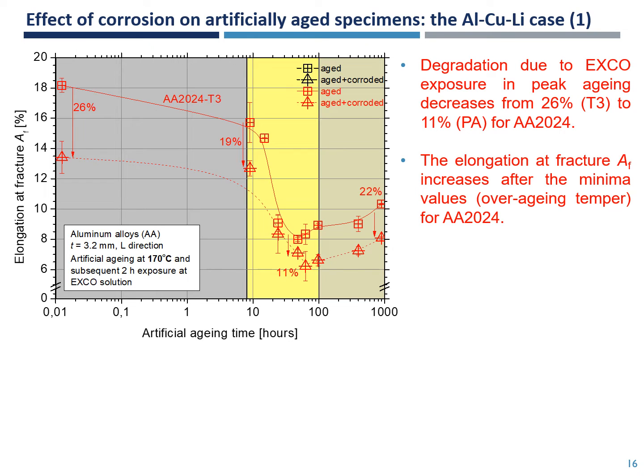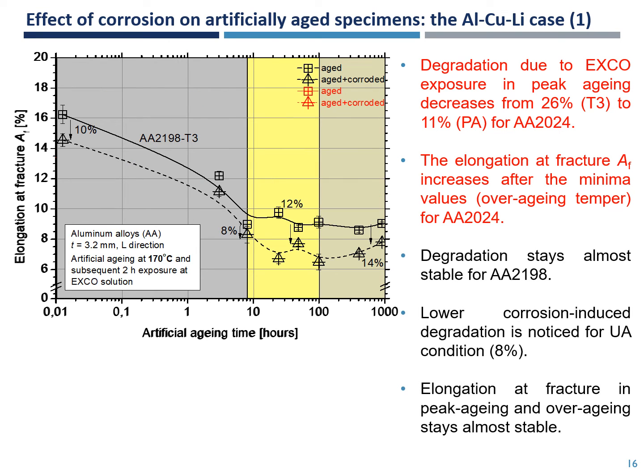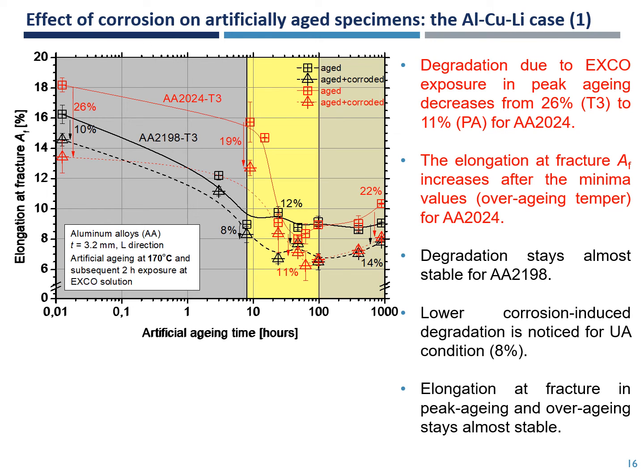As was shown in the previous slide, the lower corrosion-induced degradation of elongation fracture was evident in the peak aging regime of aluminum alloy 2024, where degradation due to EXCO exposure in peak aging decreases from 26% to almost 11%. However, for the case of aluminum alloy 2198, the degradation stays almost stable. Slightly lower corrosion-induced degradation is noticed for the under-aging condition in this alloy, and elongation fracture in peak aging and over-aging stays almost stable.